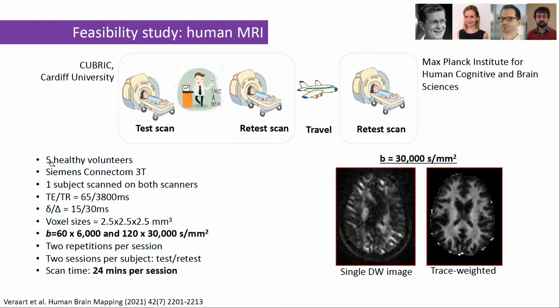There were 5 healthy volunteers enrolled in this study, and 1 subject was scanned on both scanners. However, every subject was scanned twice. There was a test scan, a break, and a retest scan. And within every scan session, we acquired 60 b=6000 images and 120 b=30,000 images. There were 2 repetitions per session, and there were 2 sessions per subject. And the total acquisition time of the test and the retest scan was 24 minutes.